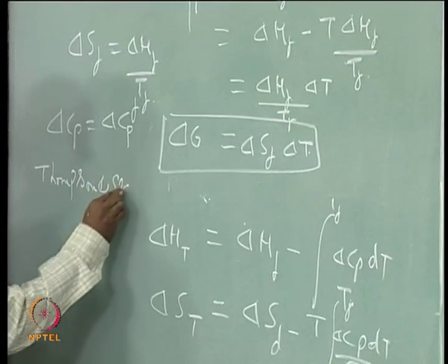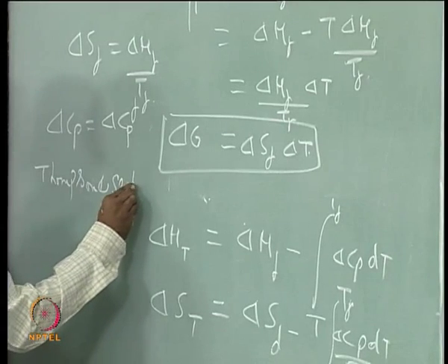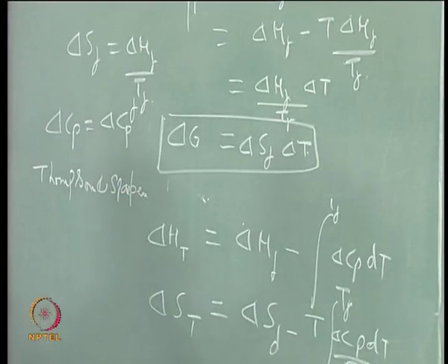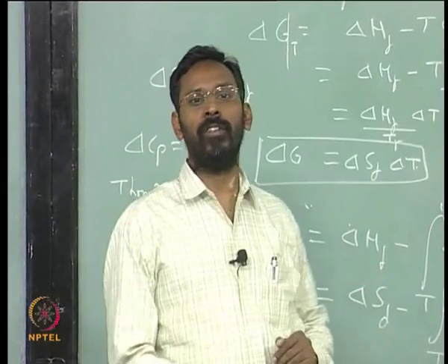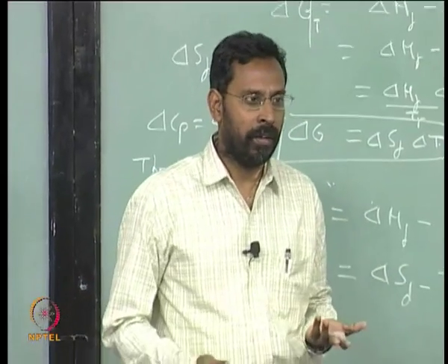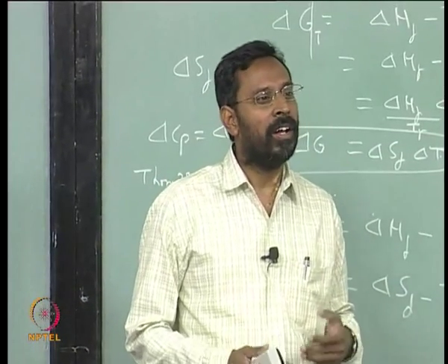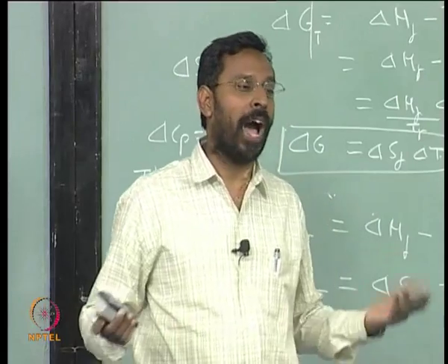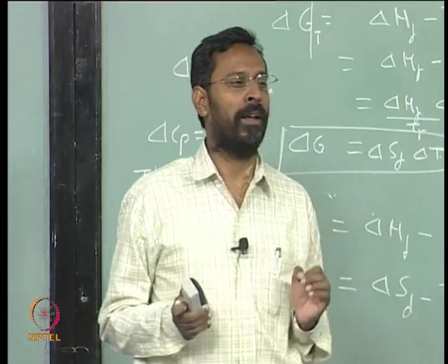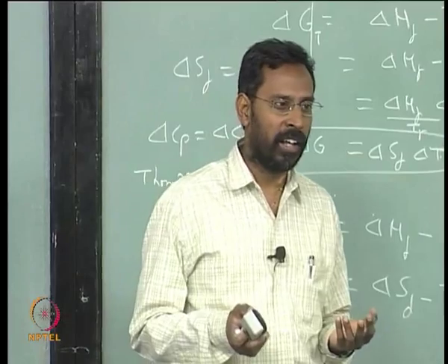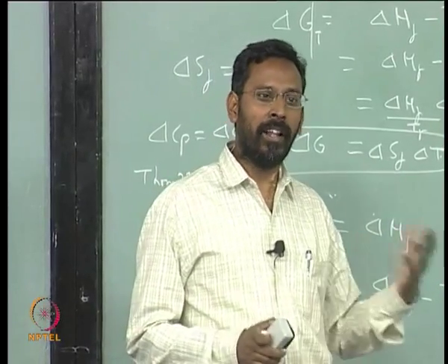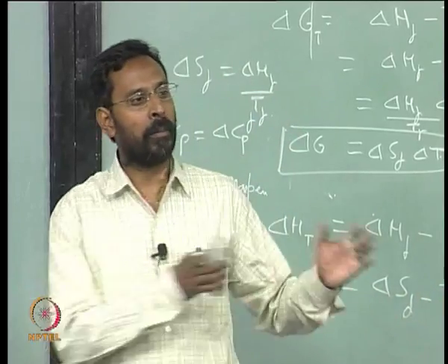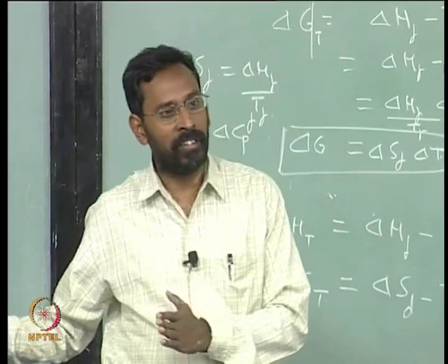Sir, is there any problem if I extrapolate the Cp of the liquid? Correct. So that is one possibility. If I know how Cp of the liquid is changing, you extrapolate it, that is one way. But for us to know whether the extrapolation is valid or not, you need some experimental validity, and the experimental validity is actually coming not from metallic systems, but from non-metallic systems.